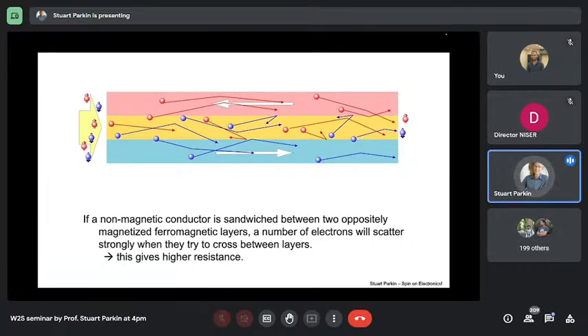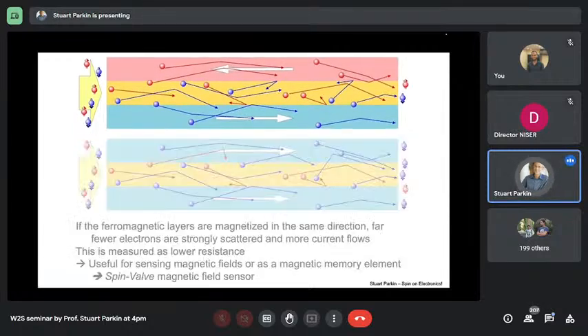But if the copper layer is sufficiently thin, the electrons can pass from one layer to the other. And so if they pass from the blue layer into the red layer, they will be scattered and vice versa. So in this case, the electrons will be scattered more strongly than in the case when these two layers are aligned parallel to one another. And so this is what we call a spin valve. In this case, by reorienting the magnetic moments, you can change the resistance of the device. And the two magnetic layers are not coupled to one another. You just rely on an external magnetic field.